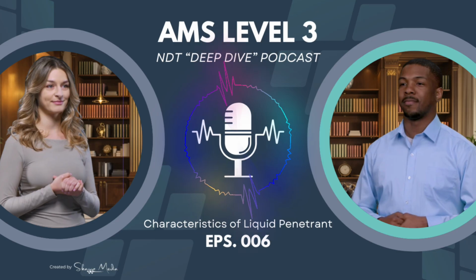Capillarity. Okay. You probably remember surface tension, right? That sort of skin a liquid has because its molecules are pulling inwards. Right. Well, that and something called the contact angle. Basically, how a drop of liquid behaves when it sits on a surface, that combination dictates everything. If a liquid spreads out completely, wets the surface fully, the contact angle is pretty much zero. If it beads up, like water on wax, the angle is large. So the crack isn't just sitting there waiting, it's actually pulling the liquid in.